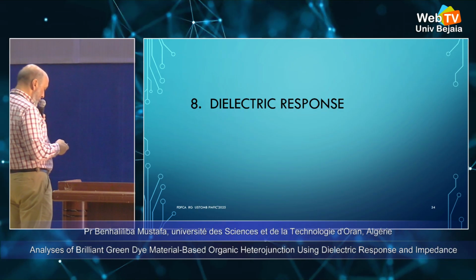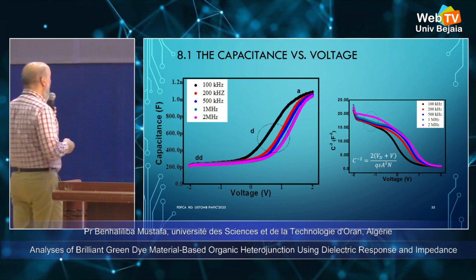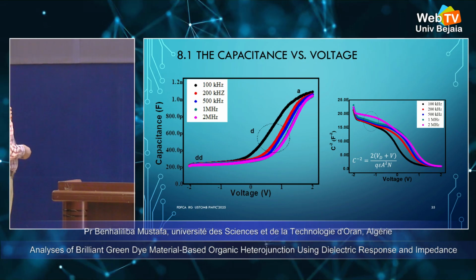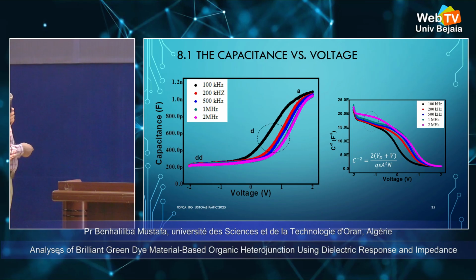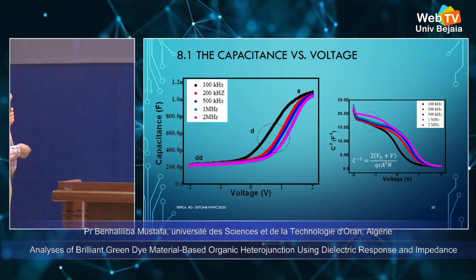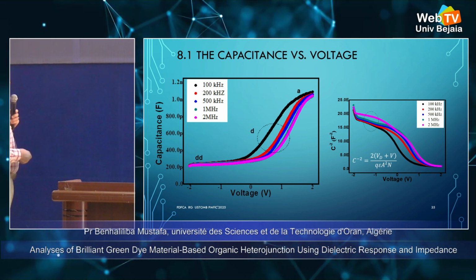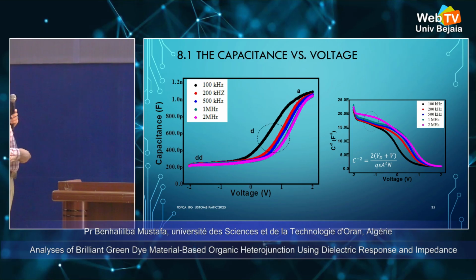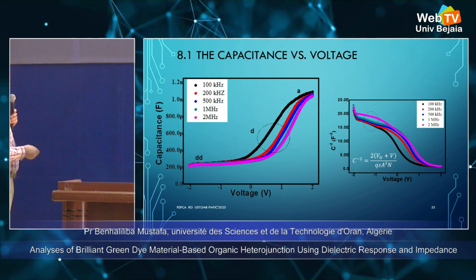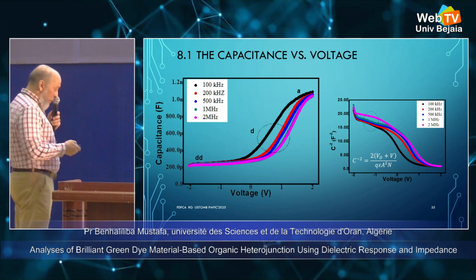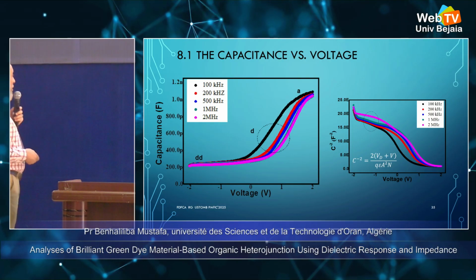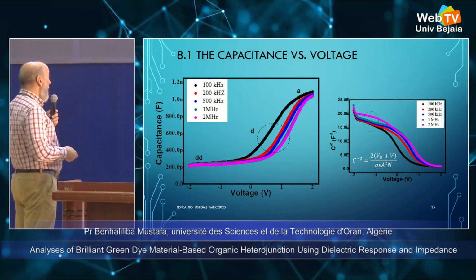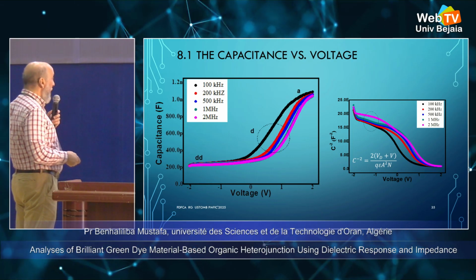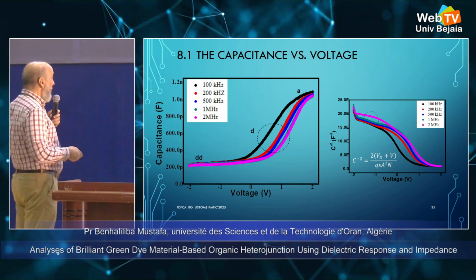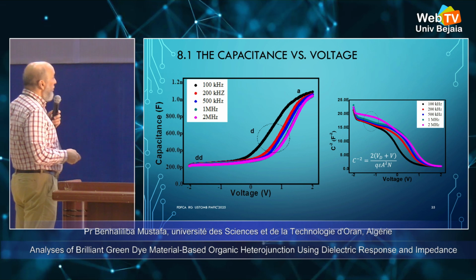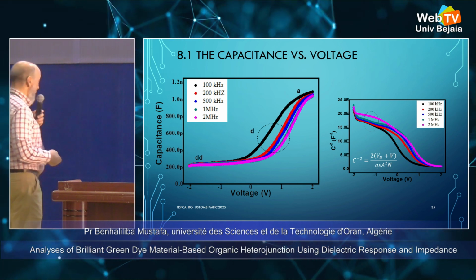For the study of the electric response, we plot capacitance versus voltage for applied frequencies from 100 kilohertz to 2 megahertz. We have this curve with the deep depletion region, the depletion region, and the accumulation of charge. We can also obtain some parameters by plotting 1 over C squared versus voltage using this formula. And we have this curve for the experimental frequencies.